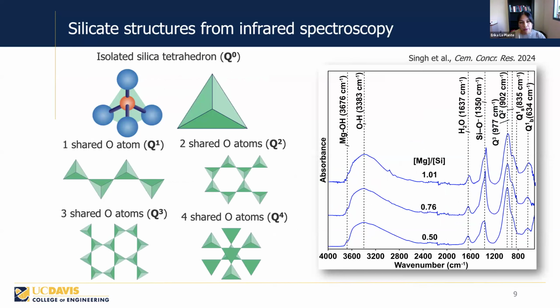So to understand the structures of this phase, we looked at infrared spectroscopy. Since MSH is a silicate mineral, we can characterize it by looking at the silicate species that are found in the solid. And for silicates, you have Q0, Q1, Q2, Q3, Q4. These different silicate species are characterized by the degree of sharing of oxygen atoms between silicon atoms. Q0 would be composed of isolated silicate tetrahedra, and these tetrahedra will be connected by cations like magnesium or calcium or others. And then for Q1, one of the oxygen atoms is shared between two silicate tetrahedra. So this forms a chain.